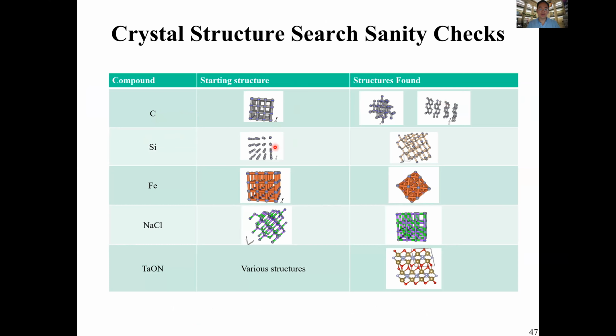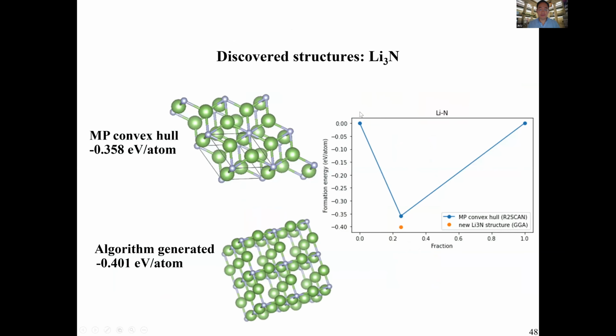If we do silicon, we're able to get the silicon diamond cubic structure. Iron, we start from simple cubic, we're able to get body-centered cubic. Sodium chloride, start from tetrahedral structure, get rock salt structure. Tantalum oxynitride gave us something pretty reasonable compared to experiment. So we start to see, can we expand upon the Materials Project structures?